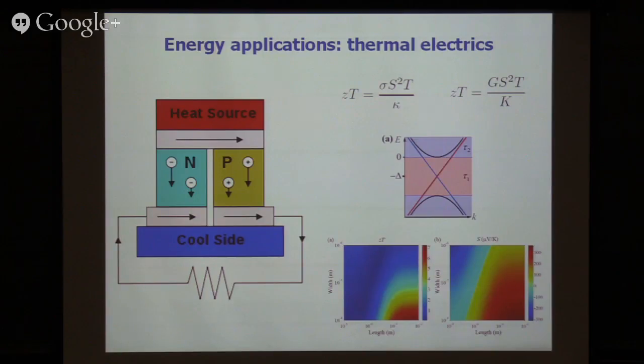But we suddenly realized that this shouldn't be the right formula. You should actually express not everything in terms of conductivity, but in terms of conductance. Instead of conductivity, you should have conductance, and instead of thermal conductivity, you should have thermal conductance. You say, why bother? I just write by Ohm's law or Fourier's law how conductance scales with conductivity. But that's only true in ordinary material. In a topological insulator, conductance doesn't scale according to the geometrical scaling of Ohm's law. So suddenly, in the figure of merit, you have another tuning parameter.